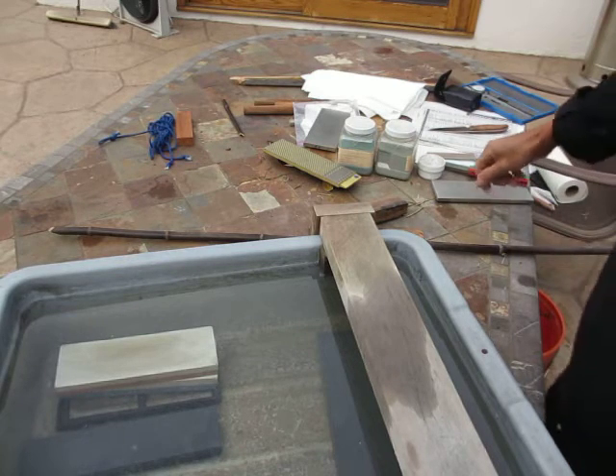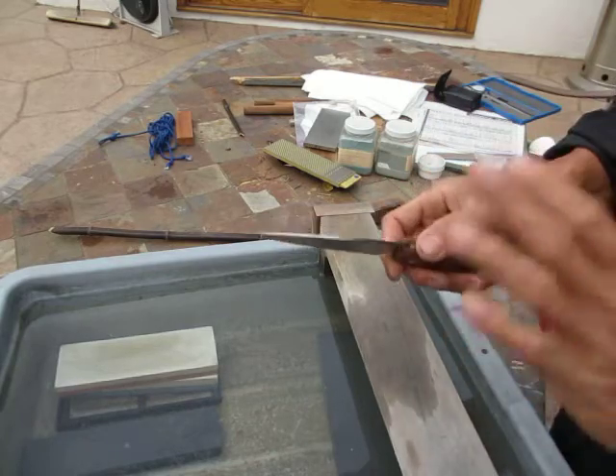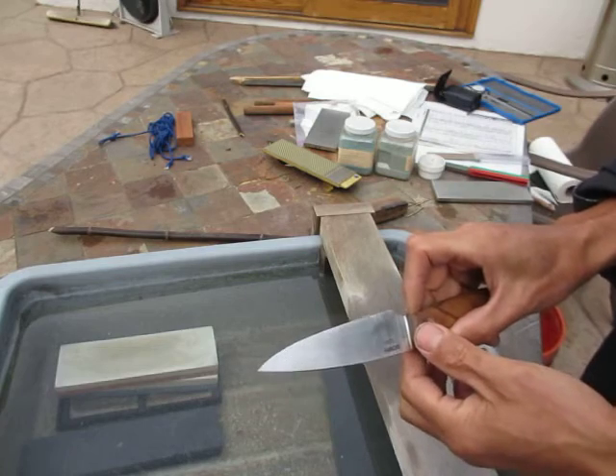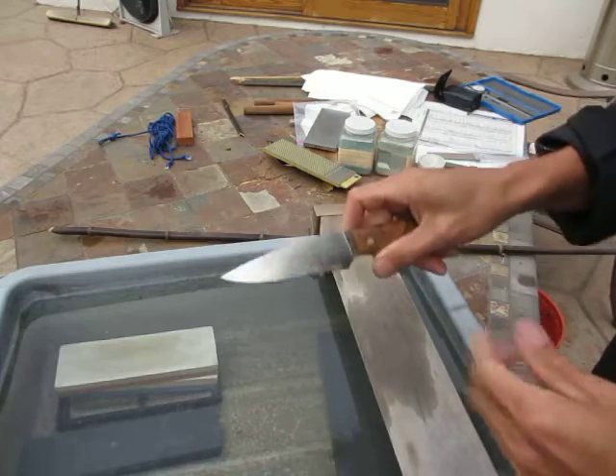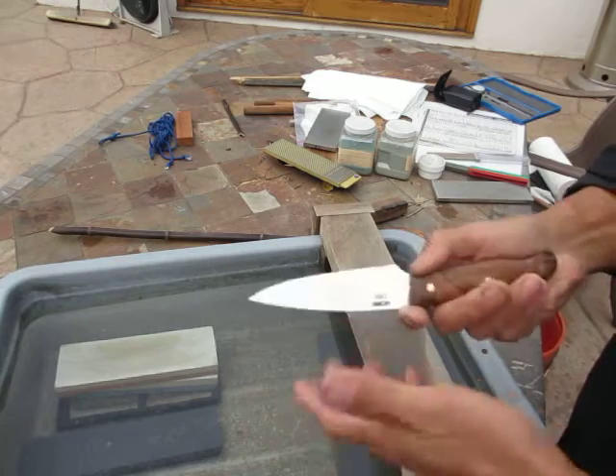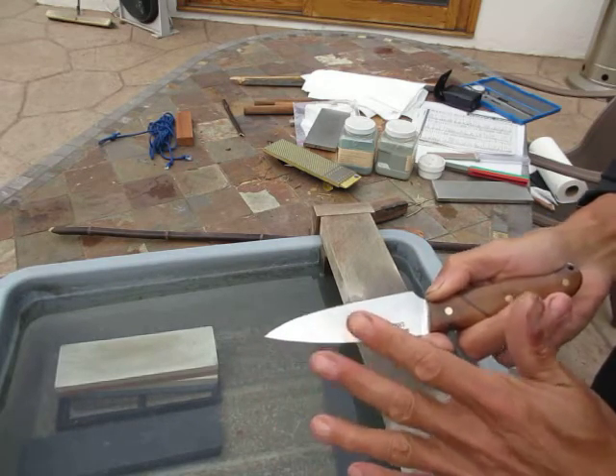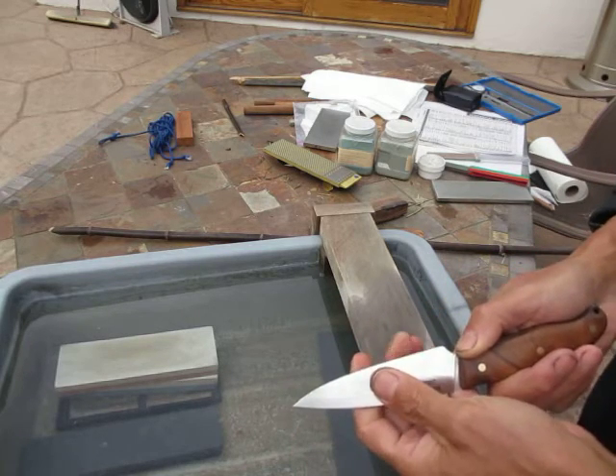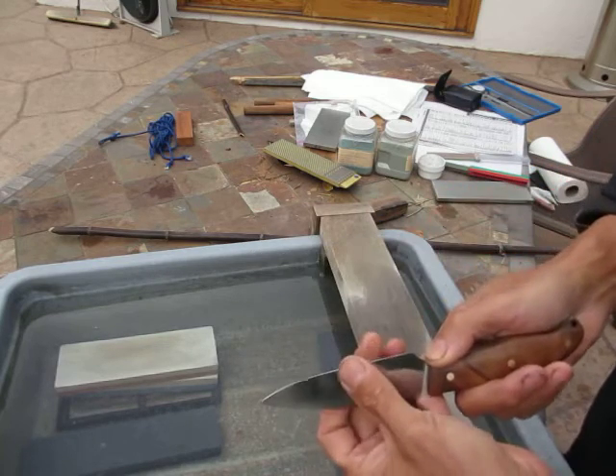Blancart Metalworks, end of October 26 or 27, and this is CPM-10V at overall 67 Rockwell hardness. This is going to be the sharpening of this high carbide volume steel — a lot of vanadium. The matrix is very hard; I estimate the matrix is probably going to be about between 62 and 64 Rockwell, and together with the carbide, it makes overall about 67 Rockwell or so.